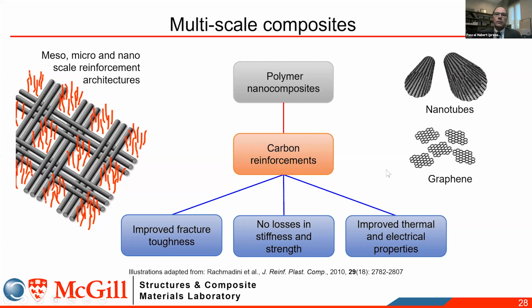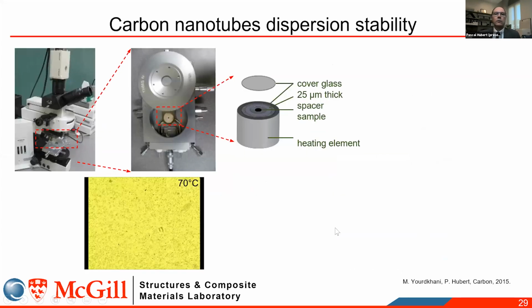But as you probably all know, in the literature, you find that it's very difficult sometimes to do this. You have issues with the dispersion of the carbon nanotube or the graphene. And the problem is that we can obtain a good dispersion to start with, but then during the process, we don't really know what's going on. And again, I found that the ability to visualize what is going on during the process gives you some good insight of what matters. And so the idea of just placing the nanocomposite on a hot stage and watching the evolution of dispersion during cure helps you to understand a bit what's happening.